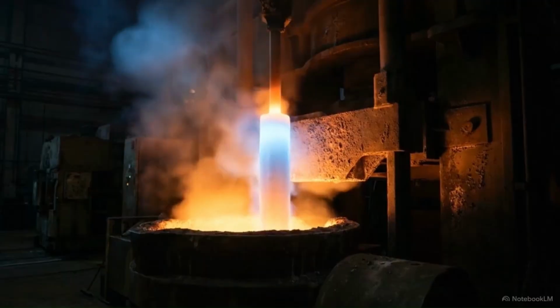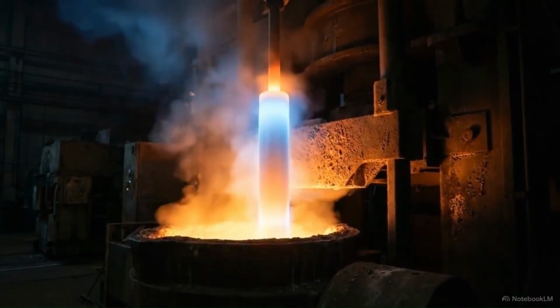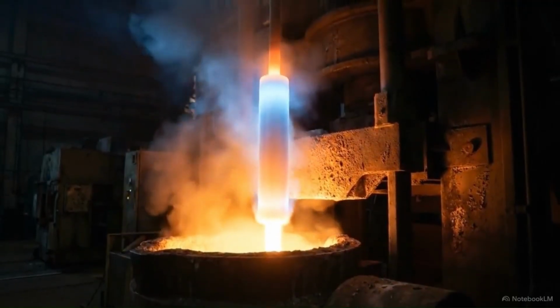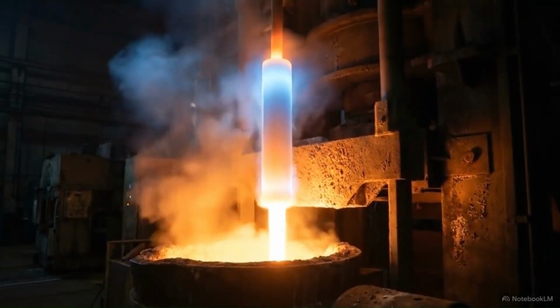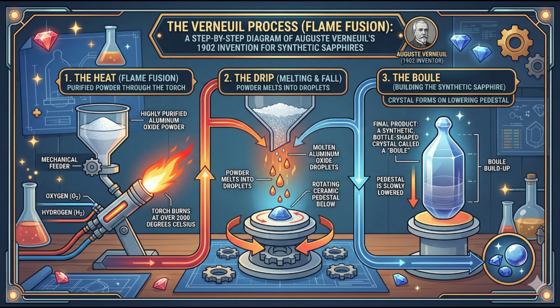Which sounds like a special attack in a video game. It does sound quite dramatic, but the mechanics are relatively straightforward. You take highly purified aluminum oxide powder, and you literally drop it through a specialized torch. A torch burning oxygen and hydrogen at over 2,000 degrees Celsius. Right. The powder melts instantly into droplets, which fall onto a little ceramic pedestal below. Like an incredibly dangerous stalagmite. Exactly like that. As the pedestal is slowly lowered, the droplets crystallize, building up a synthetic, bottle-shaped crystal called a boule.